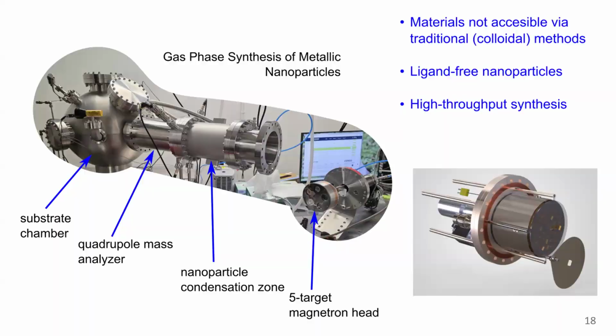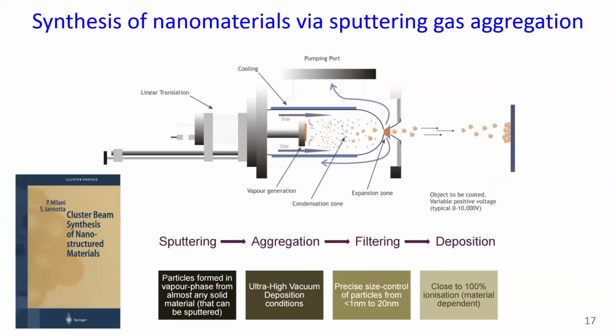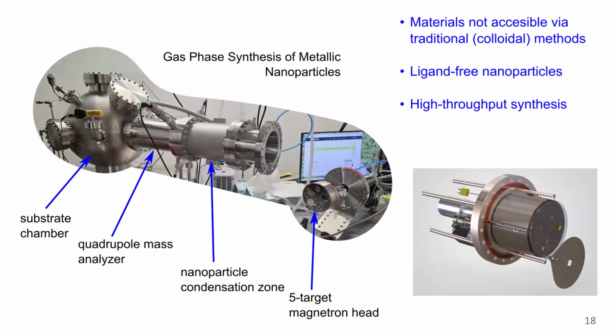Yeah, exactly. So in order to promote condensation and aggregation of the particles, this jacket is cooled with flowing water, or you can run liquid nitrogen. That's the cooling over here. But of course, the cooling in the jacket is going to be very different than the gas temperature. And so there's not a good way to measure the actual gas temperature. That's where you would need to develop some kind of a model that relates the currents on the targets, the flow rate maybe in the jacket or the temperature of the jacket to the actual plasma conditions.